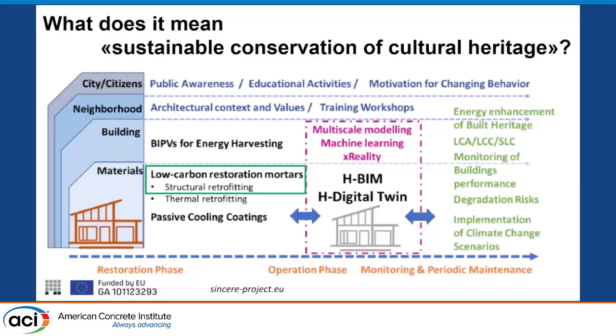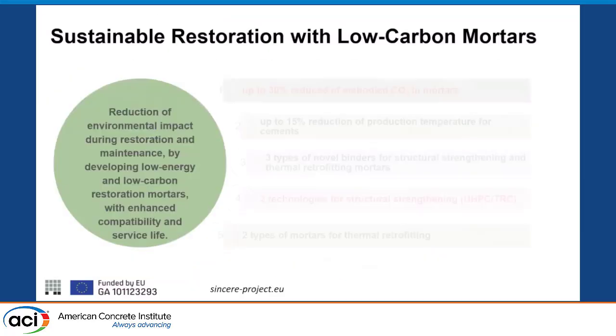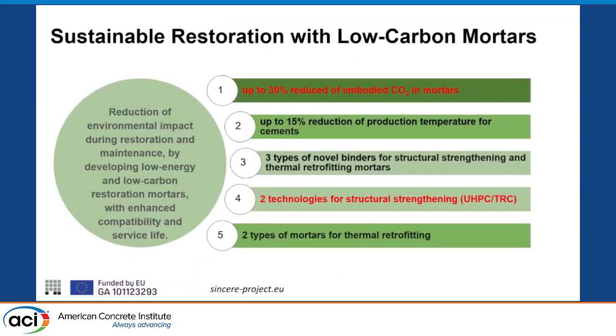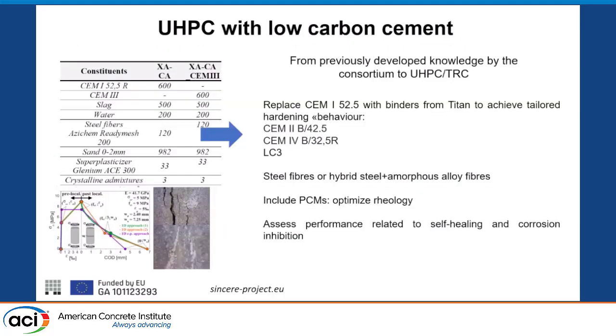And we said, okay, can we produce UHPC but not using, like it's done, CEM I, so having high carbon or high clinker cements? Can we try to make a UHPC-like material having the performance that we need, but using blended cement and reducing the embodied carbon? And our goal was that we wanted basically to reduce by 30% at least the embodied carbon of the material.